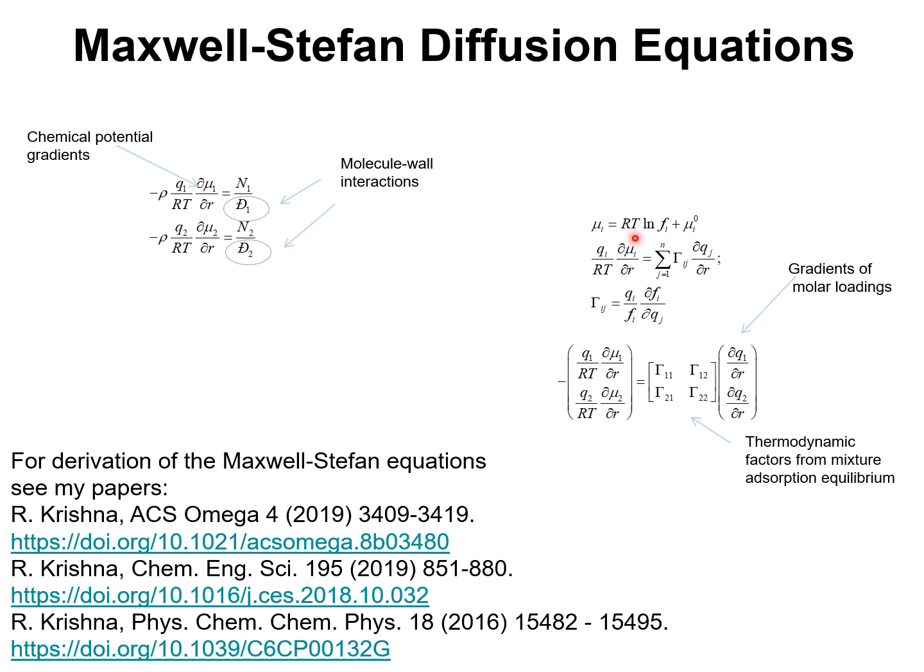Now, the chemical potential gradients are relatable to the gradients in the molar loadings by defining a matrix of thermodynamic correction factors that have elements as shown here.